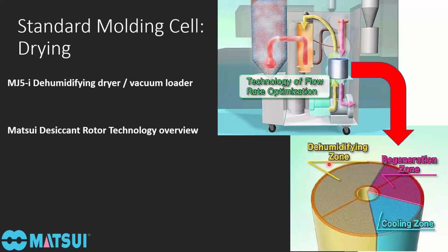After there's moisture in the desiccant, it needs to be regenerated. So during the regeneration zone, air is heated to a higher temperature to purge moisture from the desiccant. After the desiccant is regenerated, it's then cooled before being put online again.